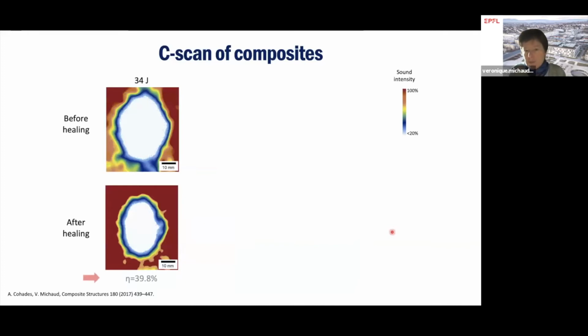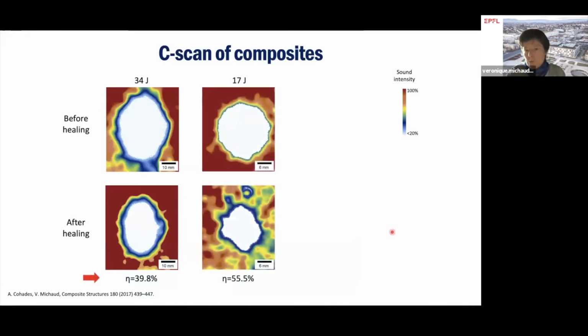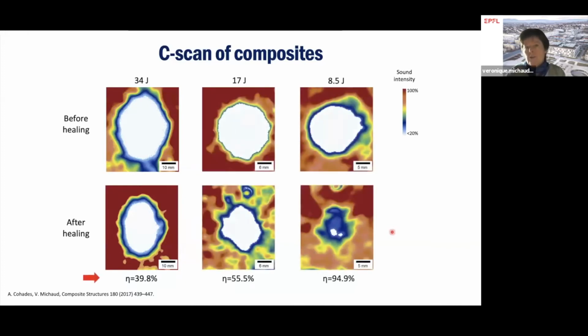We checked this with C-scans to see that we have this effect depending on the energy with a low enough energy, but 8.5 joules is already quite decent for a composite. Remember the picture I showed with 5 joules before, leading to a lot of micro cracks. With this, after healing, we got almost all the surface filled up.